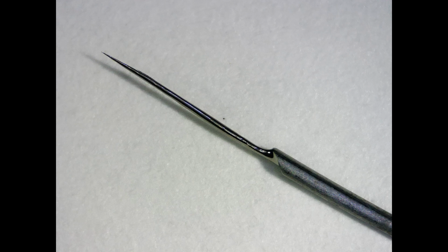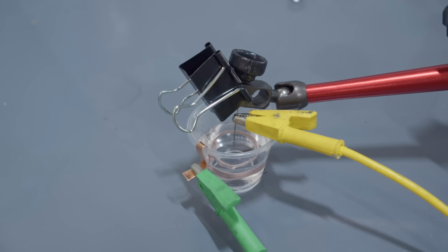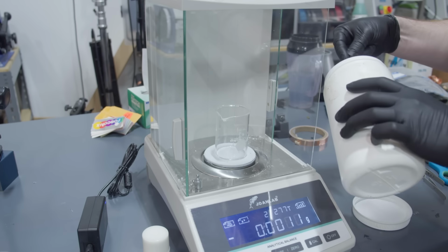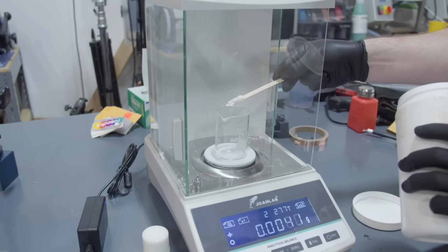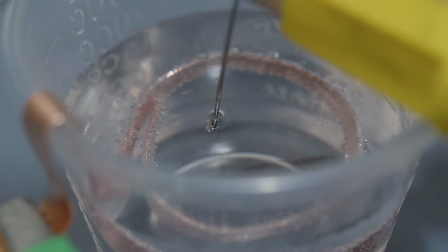The tip itself is a piece of tungsten wire that was electrochemically etched down to a very fine point. It's actually a really simple process. You just take some potassium hydroxide and apply a small voltage to the tungsten. Eventually, it will erode away and leave a sharp tip. Now, finally, it's time to test our devices.